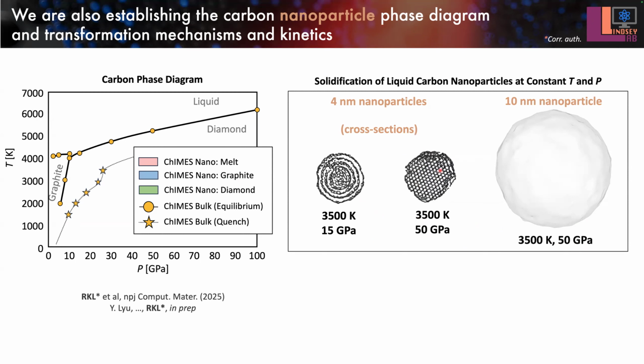And so we can take this data and collate it to form a nanoparticle phase diagram. This is what we get from our 4 nanometer simulations done thus far. Of course, the phase diagram you get is going to be a function of the size of the nanoparticle, so we're running this for a bunch of different system sizes.